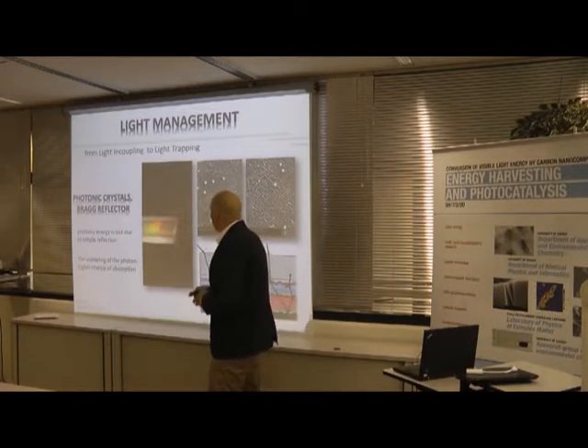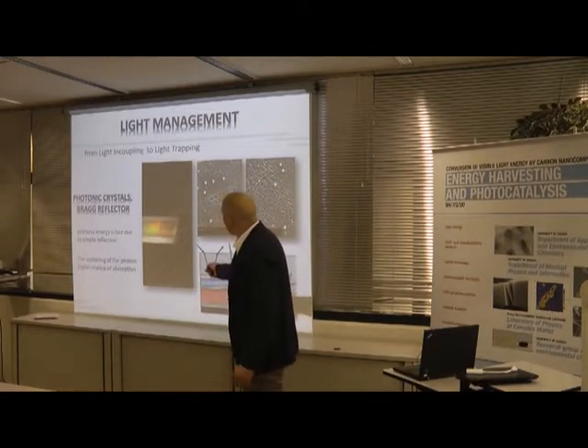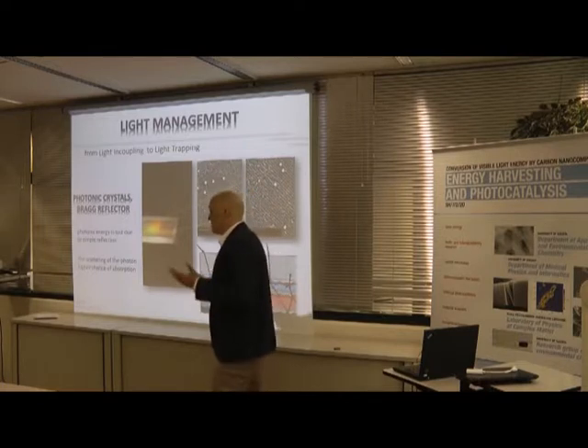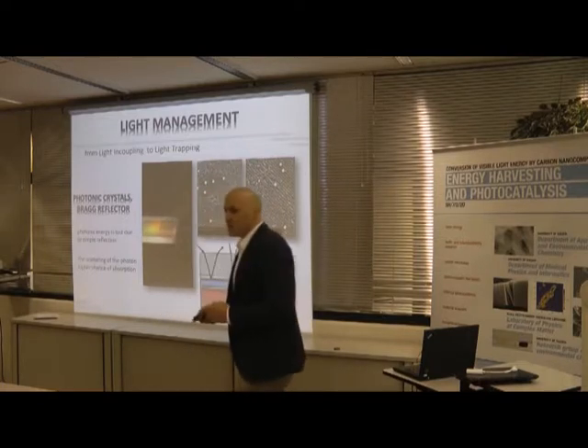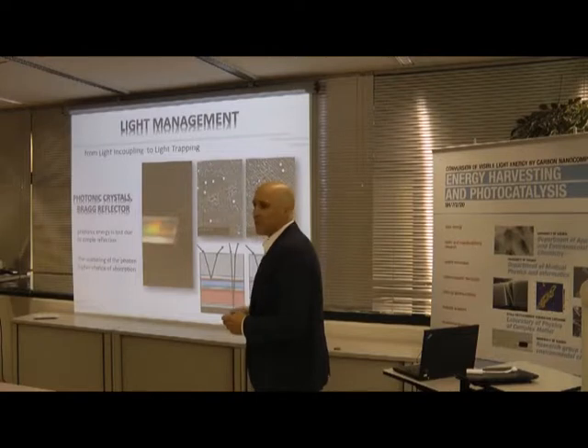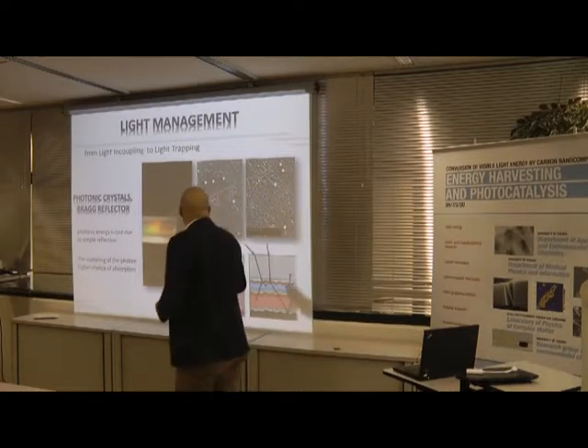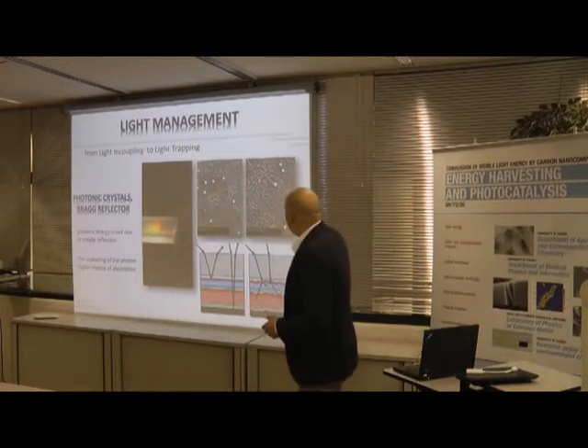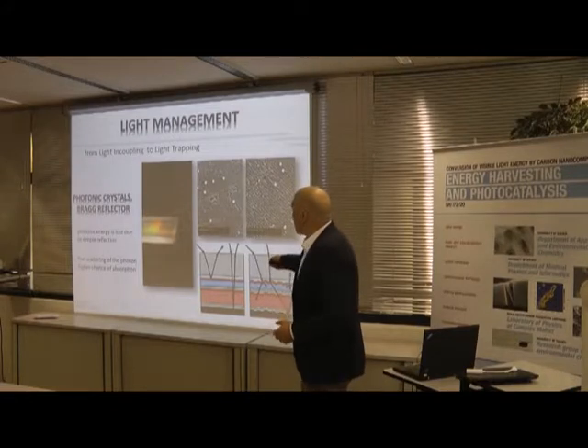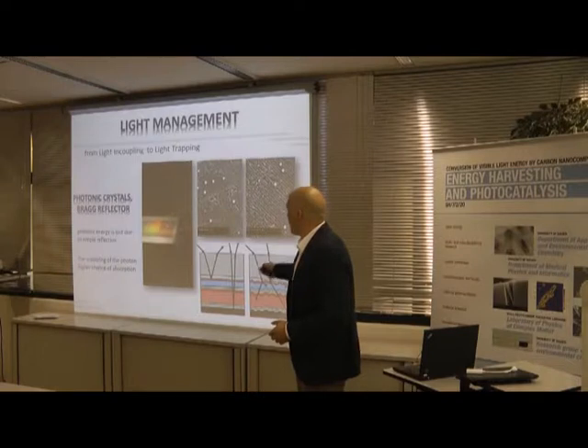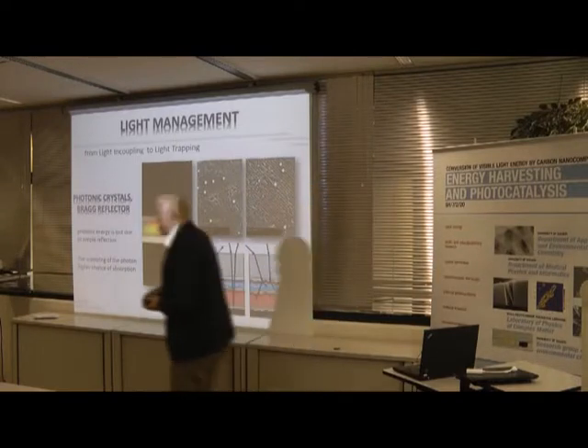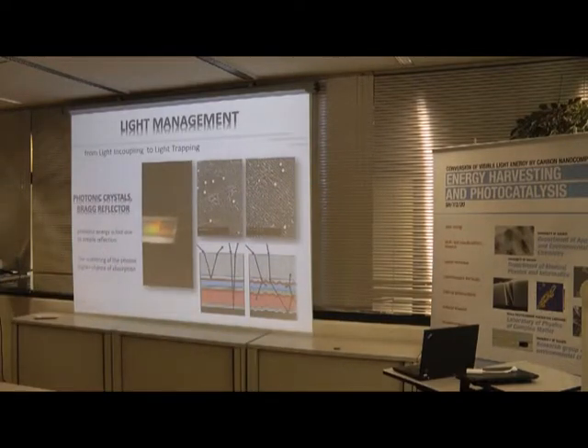Here you see a titanium dioxide film, and for the first time, at least, I'm working for the last 10 years with titanium dioxide, I have never seen colorful titanium dioxide. For the first time, by structural engineering of the surface, we render it colorful. So what you see here is an iridescent color, which you can see if you are lucky, and you shine onto this sample a light from your phone.